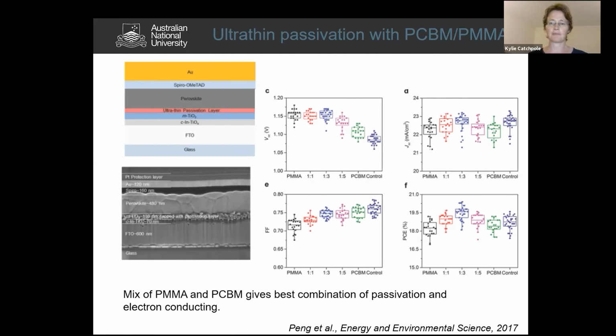So what we were doing here was a combination of PCBM and PMMA. So you can see here we have an NIP perovskite solar cell, and we have this ultra thin passivation layer between the titanium dioxide and the perovskite. And what we found is that when we included the PMMA layer by itself, it certainly improved the voltage, so that helped, but it led to a reduction in fill factor if you only have PMMA. So what we did was we had a combination of the PMMA and the PCBM, and we found that by doing that, we could